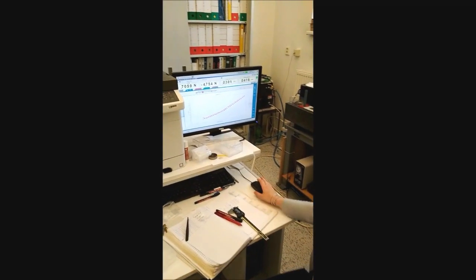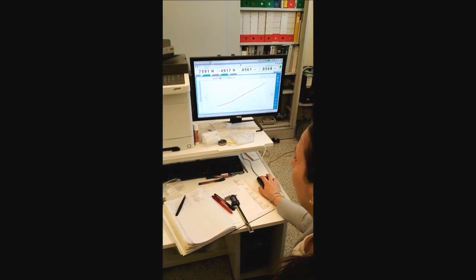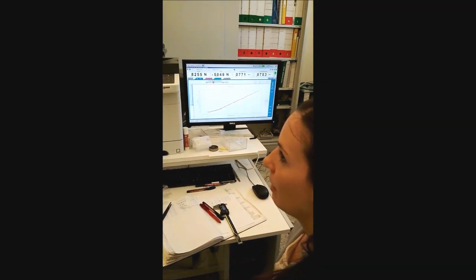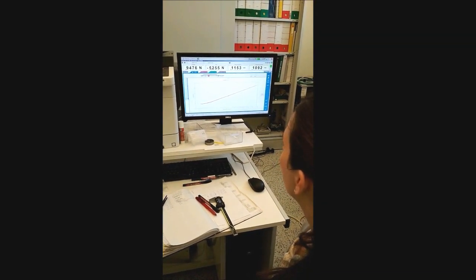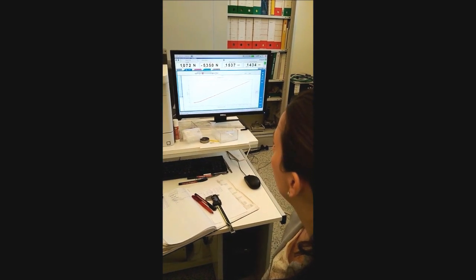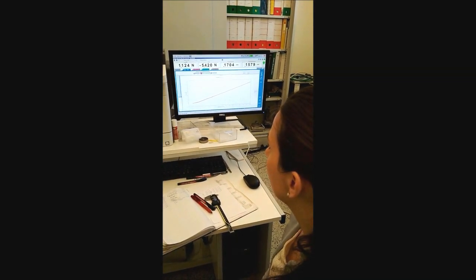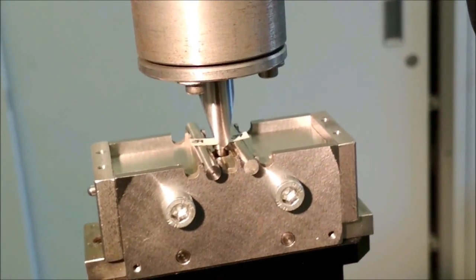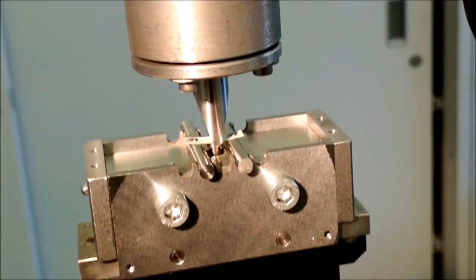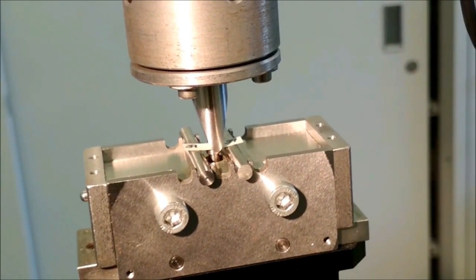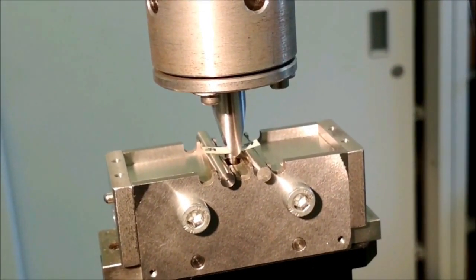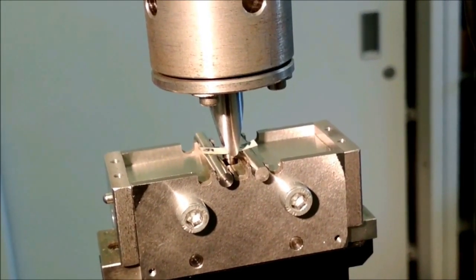You can see the graph, the loading curve, so load versus displacement. The sample will undergo 2 loading and unloading cycles. This way, I will be able to estimate also the elastic properties, elastic constants, besides the fracture strength. Now the sample underwent both cycles and the test is going to fracture. Now the test is over.